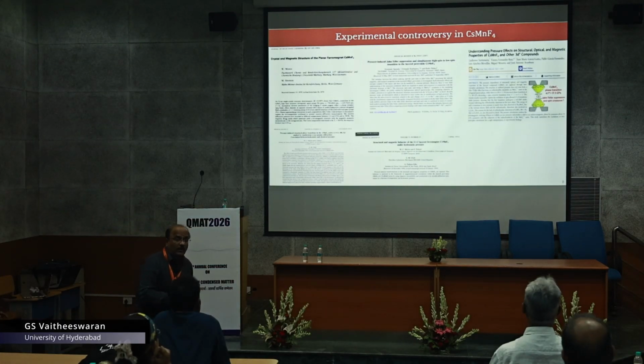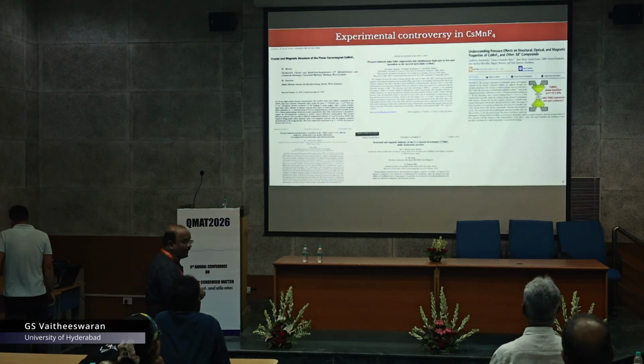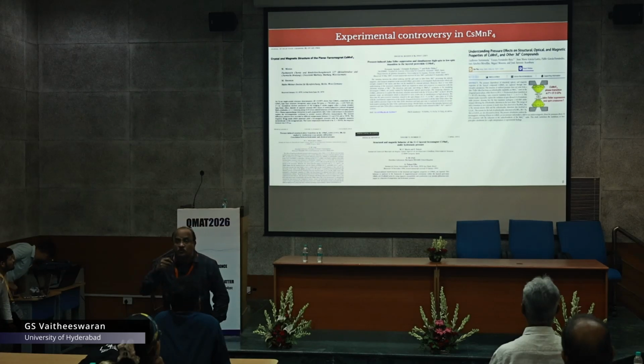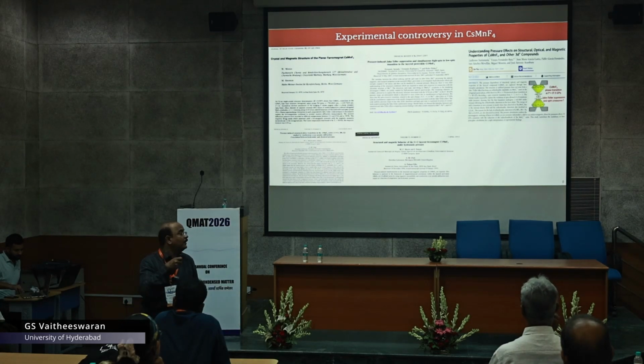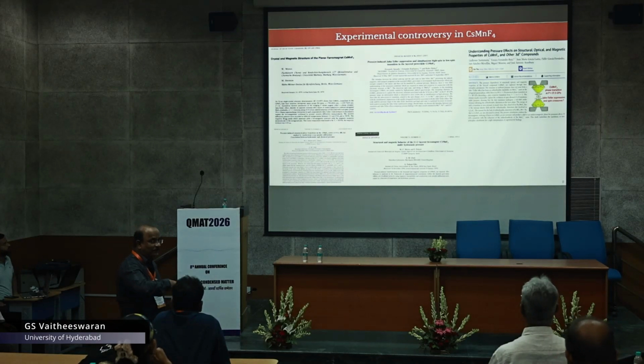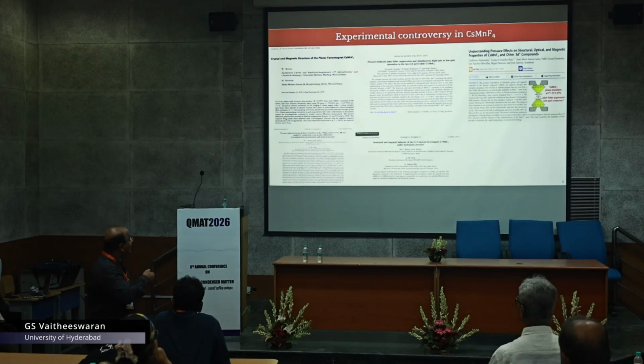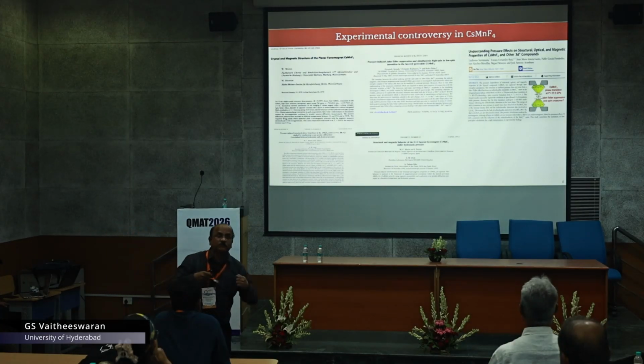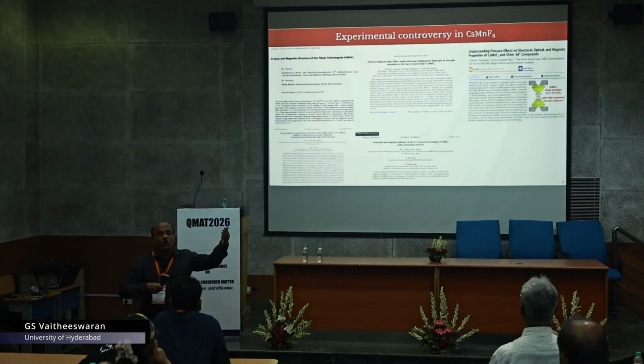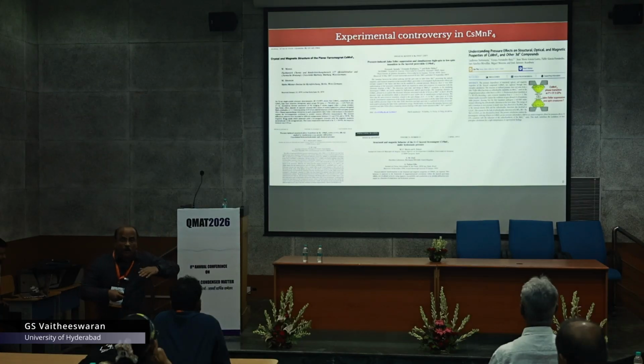And then cesium is much more interesting. There were several controversies already in the literature regarding the space group of the system. Of course, the system is reported to have a tetragonal symmetry, but each experimental group tried to contradict the other: no, you are wrong, like that. And interestingly, there were some high pressure studies in which people saw a high spin to low spin kind of transition, which is also reported experimentally, and this may lead to some kind of structural transformation, which can also destroy the magnetism associated with the lattice.